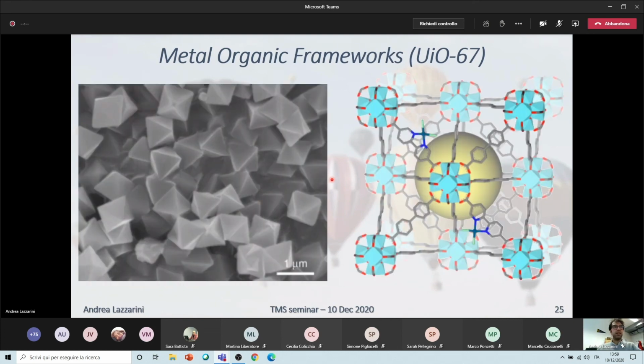We were interested not only in the grafting of the metal ion on the bipyridine ring, but also in the shape and the size of the cavity, because as you can see, this is a very large space in which you can trap a metal nanoparticle. These holes inside the structure of the MOF, these cavities, can act as a templating agent for the metal nanoparticles in order to provide a very specific size of the particles.